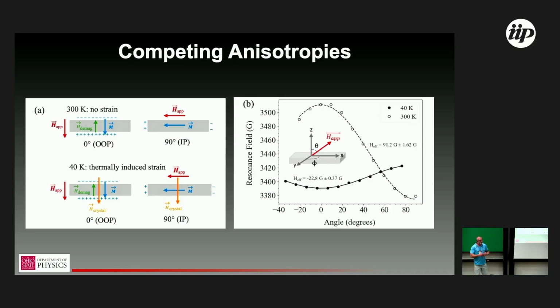And so this again was a learning experience for me and my group in dealing with these systems, in that it taught us two things. One, I thought of uniaxial anisotropy as up and down, right? It's degenerate, but in the formalism, there's a sign associated with it, and I never really understood how that could be physical. Well, this is how. Because you need to keep track of, is your crystal field parallel or anti-parallel to your demagnetizing field? And it turns out it just must be true for these materials that it's anti-parallel, so that as I systematically increase the strain, I can come to a regime where those two arrows exactly cancel out. So the shape anisotropy and the crystal field anisotropy exactly balance.